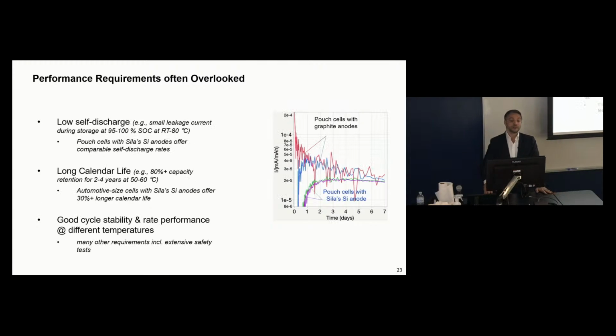In addition, there should be low self-discharge. And so, again, typically you heat the battery to certain temperatures and look at the leakage current. And again, you have to make sure that the materials you develop, in our case, silicon anodes, would have a lower or at least the same leakage current compared to the high-performance graphite anodes.